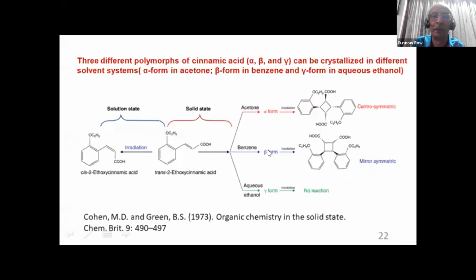In acetone, they form the alpha form. In benzene, they form the beta form. And in aqueous ethanol, they form the gamma form. And the gamma form shows no reaction between these two. These two show what are known as solid state reactions. There is a dimerization that occurs between these two double bonds, a classic 2+2 dimerization, which forms a 4-membered ring. It is found to form a centrosymmetric dimer in the case of the alpha form, a mirror symmetric dimer in the case of the beta form, and no possibility of forming this in the gamma form. So the three states in this particular case are different from each other, and so there are 3 different polymorphic forms.